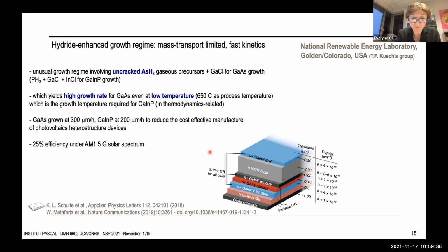So it is mandatory to reduce the cost of III-V epitaxial growth in order for these solar cells to reach larger markets. First of all, HVPE replaces the quite expensive group III metal organic precursors used in MOVPE with lower cost elemental sources, and offers also conditions where growth rate as high as 3 microns per hour can be reached. And as a matter of fact, Ketch groups in the USA used a growth regime that they call hydride enhanced, which involves uncracked arsine.